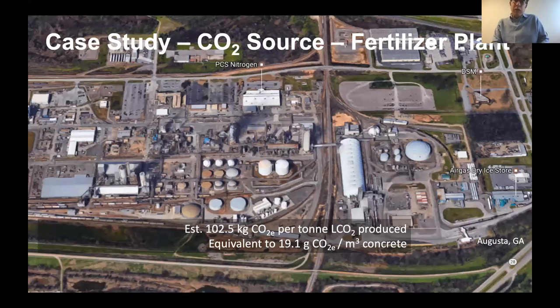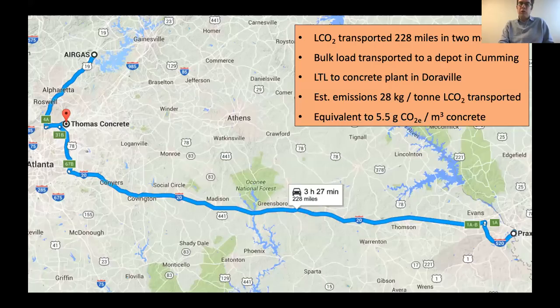So as a case study, what this would look like in practice: there's a producer using our technology in Georgia, and they get their CO2 from a fertilizer plant. So if we say the energy input to get a ton of CO2 emits about 100 kilograms of CO2, and we can make that on the unit basis of the meter cube of concrete according to the dose we use. That CO2 is then transported as a bulk load to an air gas facility in Cumming, Georgia, and then in what they call a less than load format to Thomas Concrete.